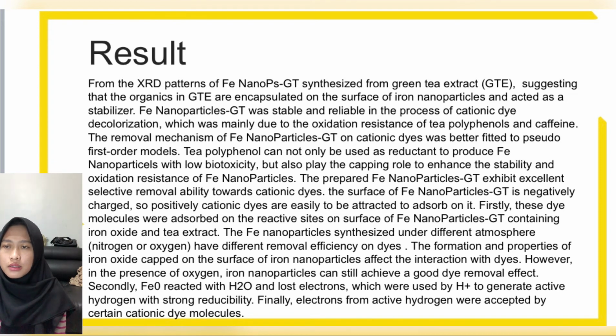The removal mechanism of FeNPs-GT on cationic dyes was better fit to pseudo-first order models. The polyphenol can not only be used as reductant to produce Fe nanoparticle with low biotoxicity, but also play the capping role to enhance the stability and oxidation resistance of Fe nanoparticle. The prepared FeNPs-GT exhibit excellent selective removal ability towards cationic dyes.